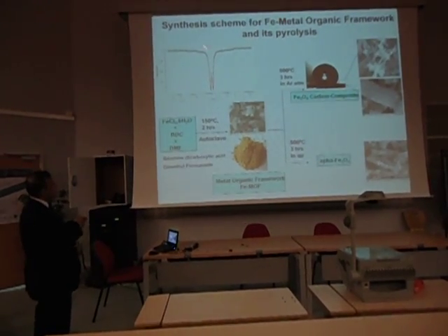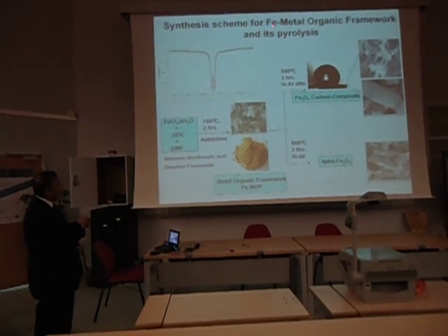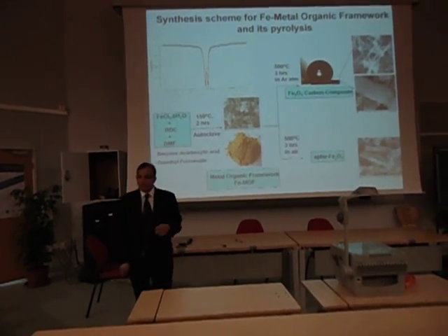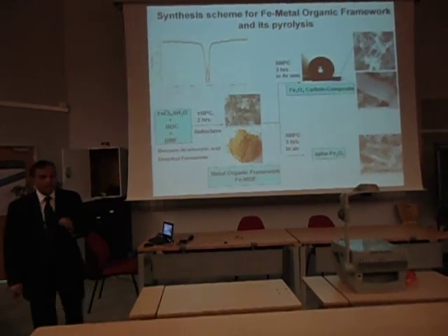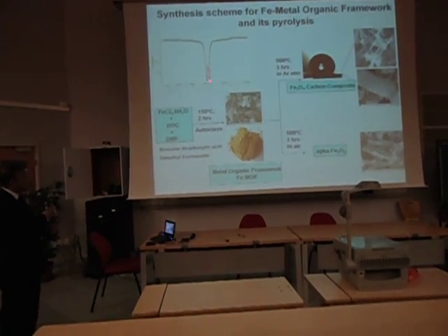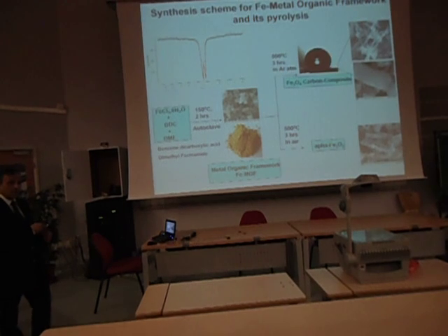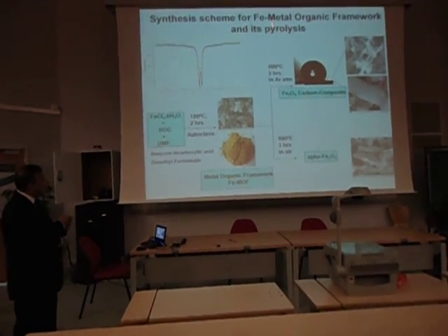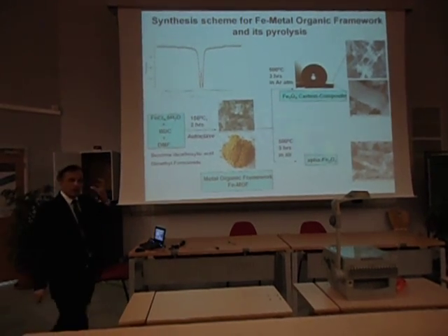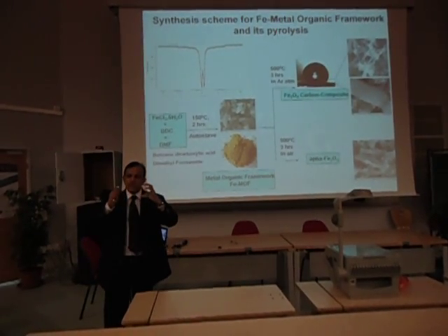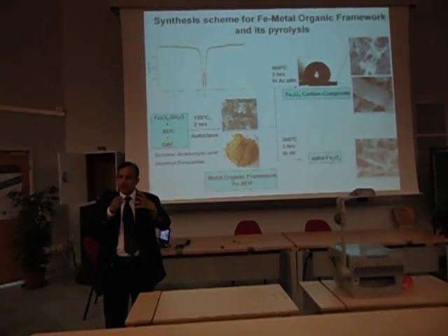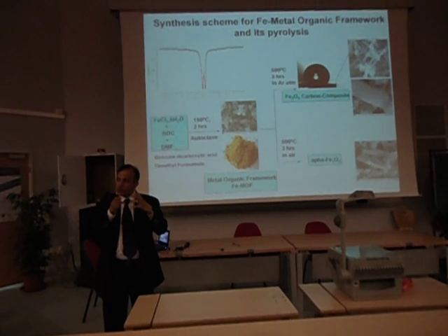One of my students used an Fe containing metal organic framework, a MOF system, an iron containing MOF, and of course, he used Mössbauer spectroscopy to see that it is in the Fe3+ state, which is what is expected for this particular MOF. Then he tried to develop carbon materials starting with this MOF. These MOFs are, as many of you would know, very open structures, and when they crumble under pyrolysis or under radiation treatments, they form highly porous structures in this way.